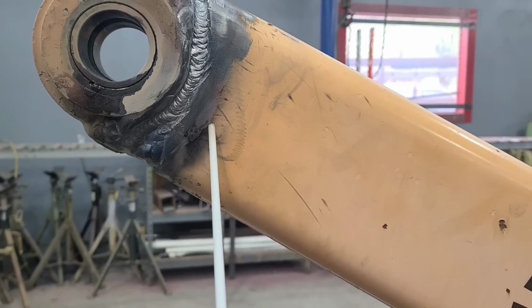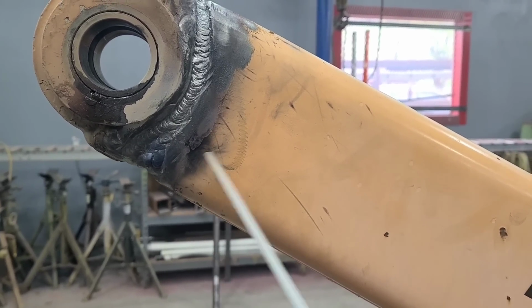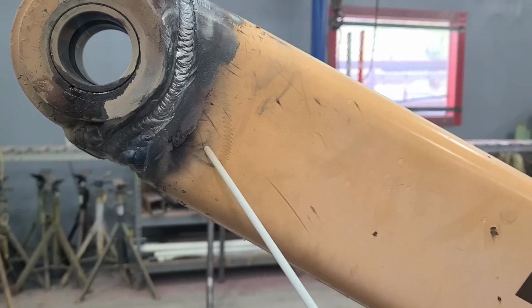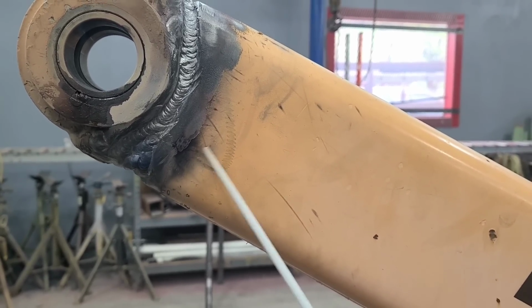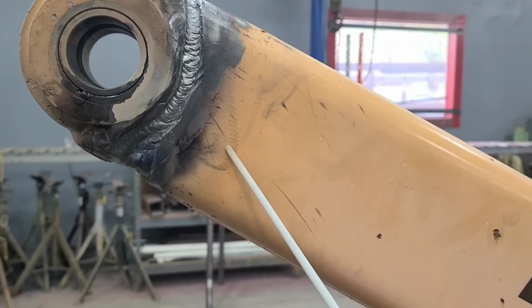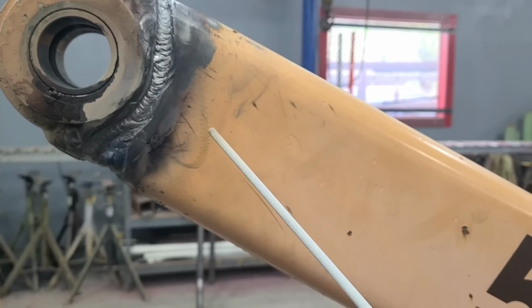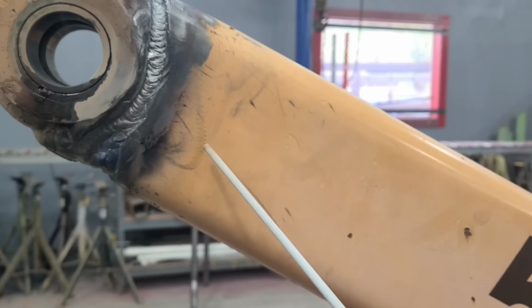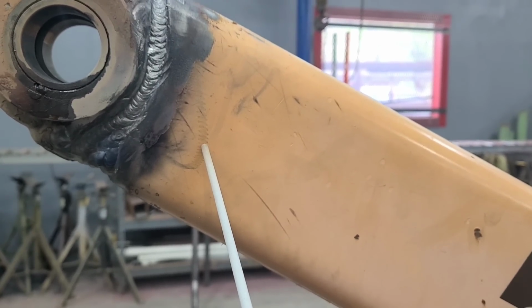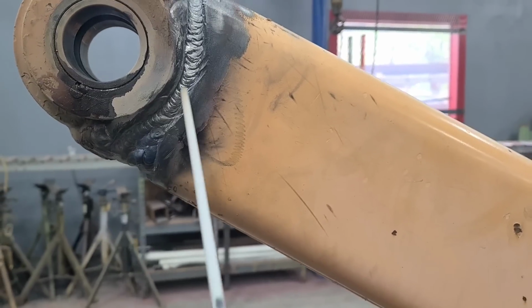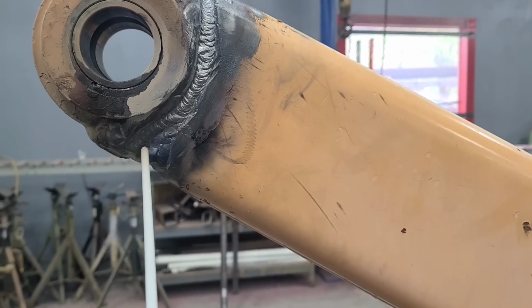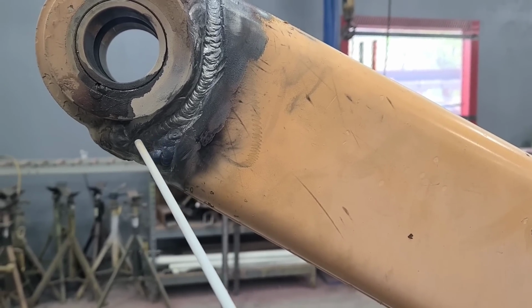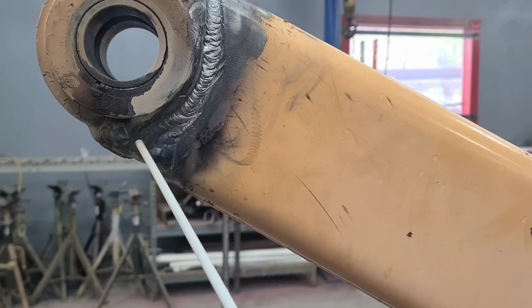Remember, as we weld, especially with our stick, we can manage the heat a little bit with our arc length. The longer the arc, the more heat. The shorter the arc, the less heat. So on these vertical welds, if our heat's set correctly, you're going to start out with a bit of a long arc to get it going.